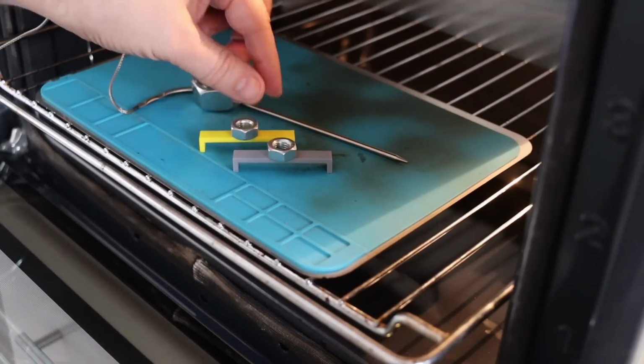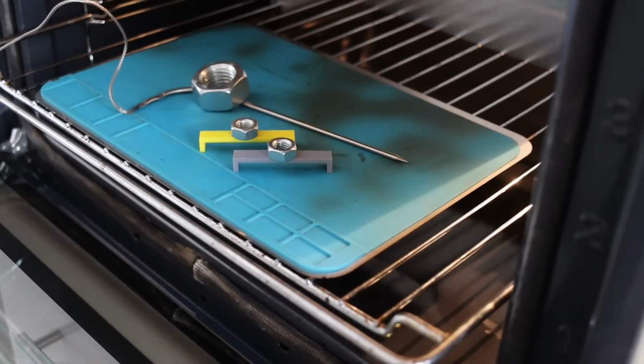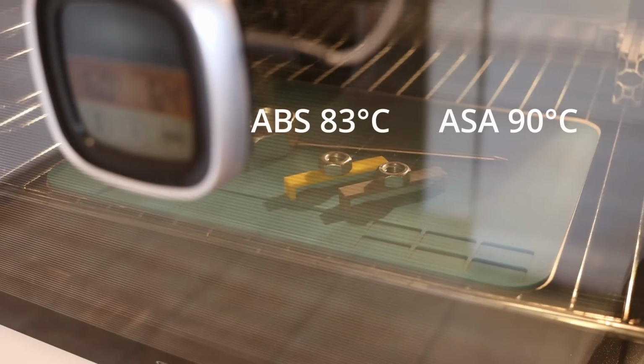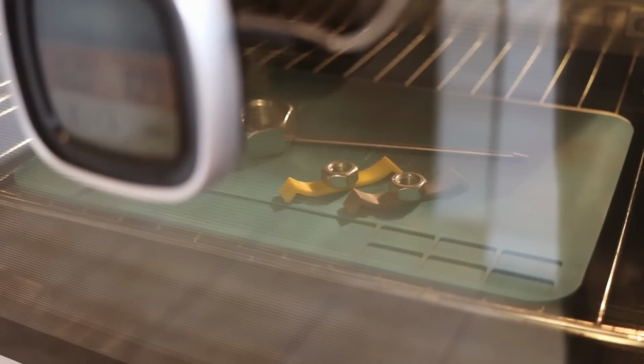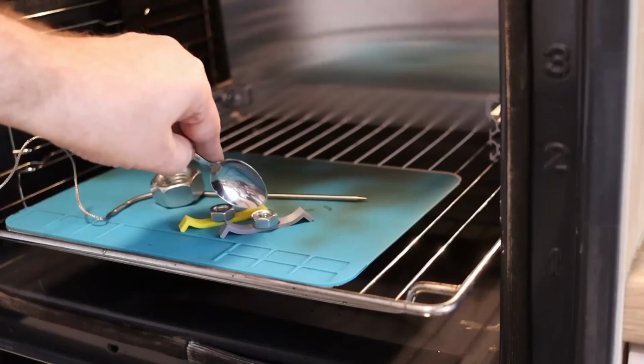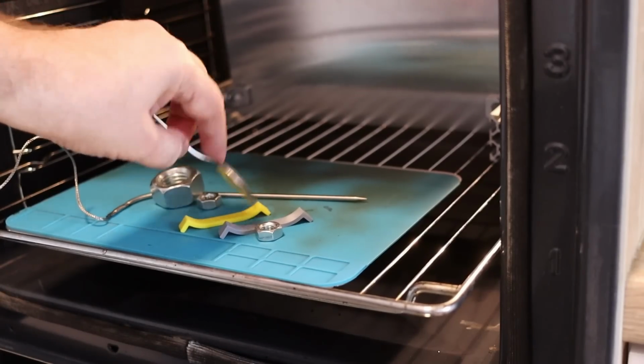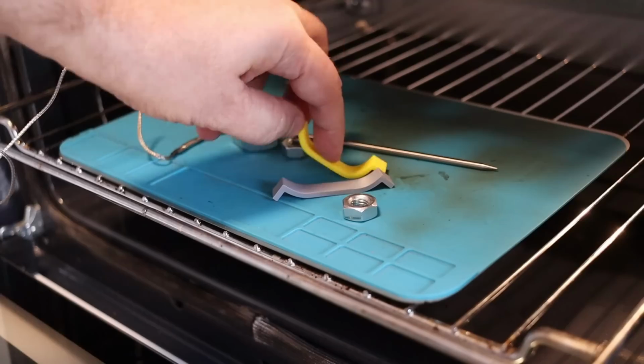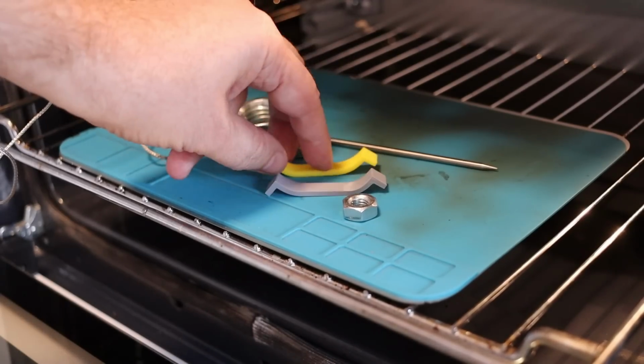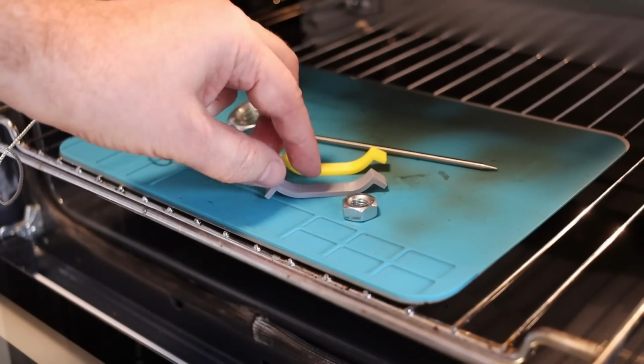The temperature test in the oven. I want to record the temperature of the first deformation. M10 nut as a small load is placed on these test objects and I'm following the temperatures, and approximately at 83 and 90 degrees Celsius these test objects started with deformation. First I checked them with the spoon, but after only half minutes I could even touch them with my fingers, and for the feeling the ABS is softer compared to the ASA.